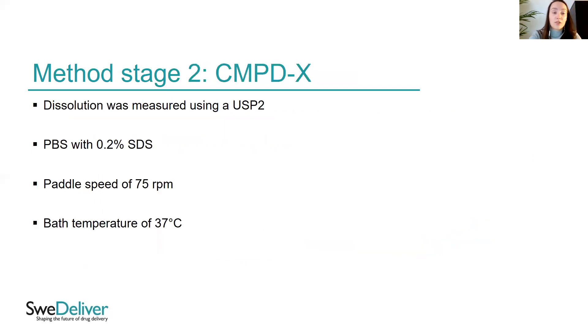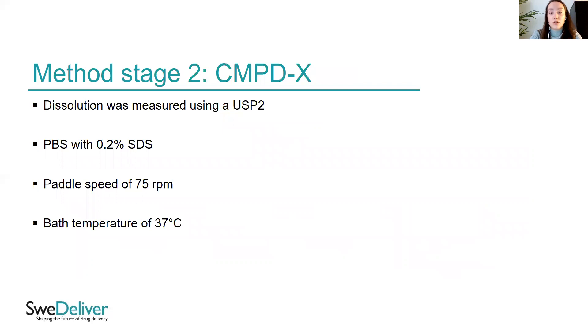For the second stage — the CMPD-X loaded particles with the same particle size but different pore sizes — dissolution was measured using a USP 2 apparatus in PBS with 0.2% SDS, a paddle speed of 75 RPM, and a bath temperature of 37 degrees Celsius.